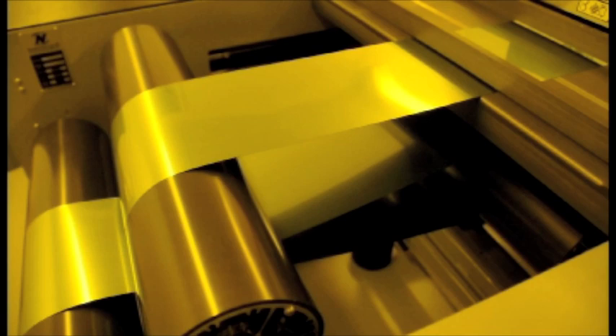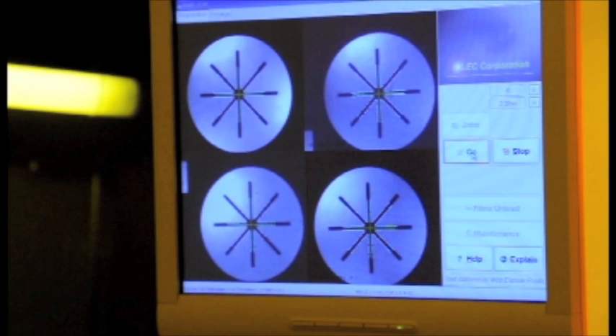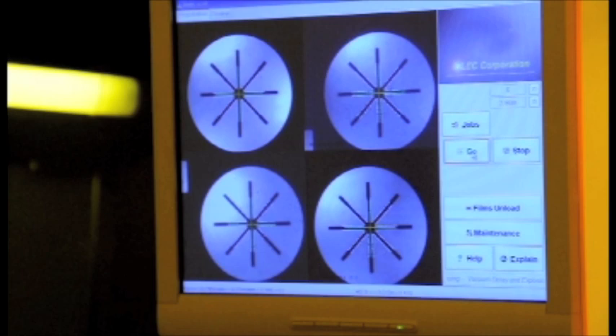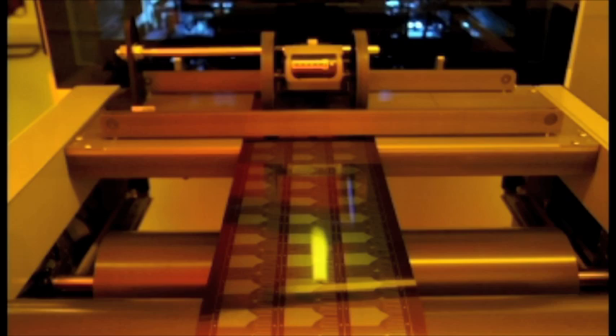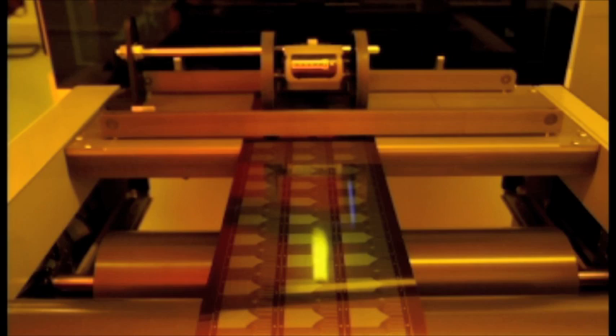CCD cameras using fiducial targets plotted on the tooling register the top and bottom films within 5 microns prior to every exposure. In reel-to-reel printing, panels approximately 500 mm in length are sequentially exposed and advanced by precise linear motors. Again, the CCD cameras are employed to find fiducial targets printed on each panel and align each panel to the next within 13 microns.